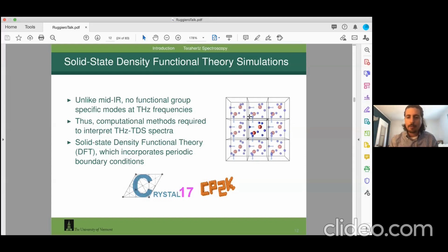What that means, and what we do, is we simulate basically the contents of one unit cell. We even reduce it further by taking symmetry into account. So we simulate the symmetry independent unit of a unit cell, and that unit cell has translational symmetry in all 3 dimensions. We take that into account in our simulations through Bloch's theorem. So we simulate the unit cell, and then we do some math tricks to replicate that in all 3 dimensions. What that means is all of the forces in that simulation are real. It's a real periodic method.